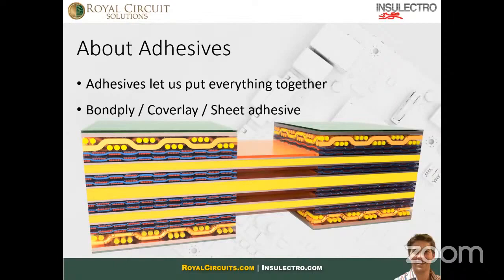So where we have copper cables that are exposed and not encapsulated in our rigid sections, we'll laminate coverlay over those open areas to prevent the circuits from getting shorted by water or any kind of outside material. When we go inside the rigid section, we don't have the coverlay there because it's difficult, one, to bond to polyimide materials, but also, second, we don't want that acrylic adhesive in the rigid zone. So we'll selectively cut that material out of the rigid area.